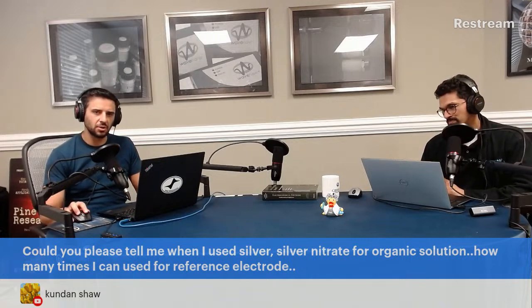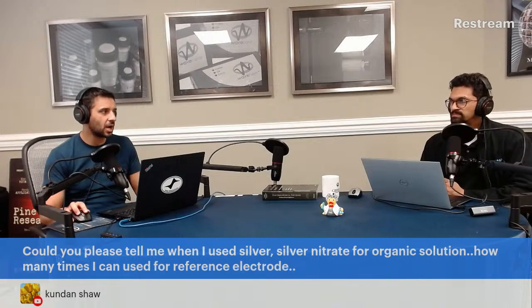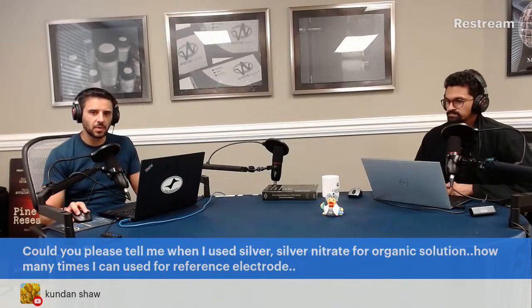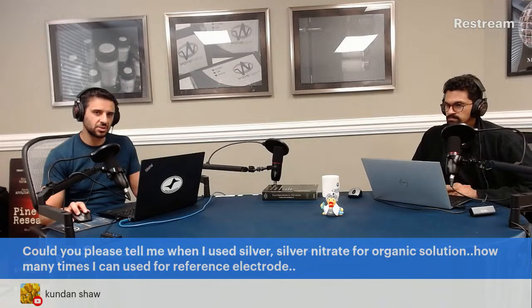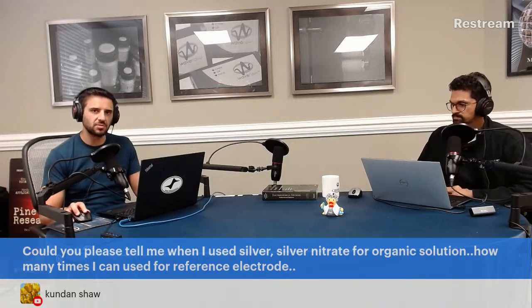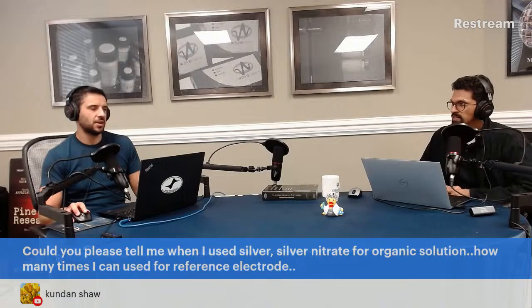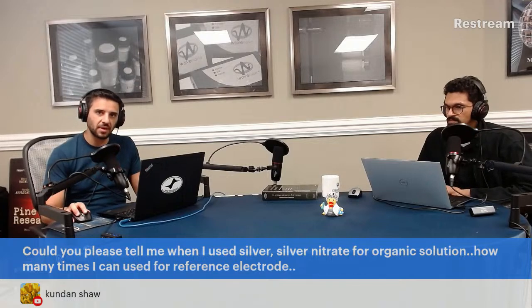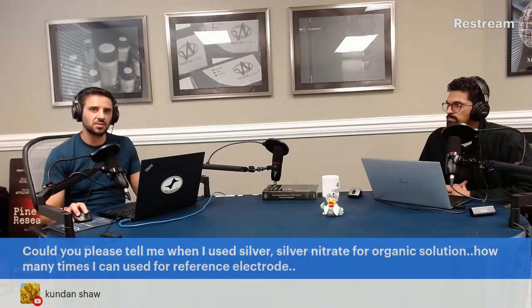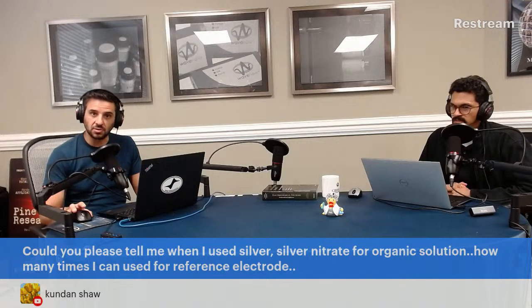Mostly you're looking for that drift, right? I mean, there can be an offset, which you'd potentially be concerned about because it would mean that the chemistry has changed or some other species is affecting the thermodynamics. But to a certain extent, if your reference electrode is exhibiting a stable potential, it doesn't matter what it is as long as you know what it is. If it's drifting, that's the big problem.